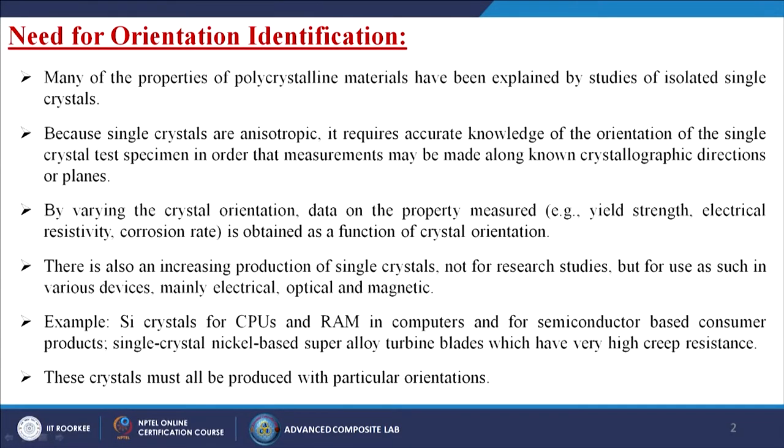As we know, many of the properties of polycrystalline materials have been explained by studies of isolated single crystals, because single crystals are anisotropic in nature, which requires accurate knowledge of the orientations of the single crystal test specimen so that measurements may be made along known crystallographic directions or planes. By varying the crystal orientations, data on the property measured, like yield strength, electrical resistivity, corrosion, etc., is obtained as a function of crystal orientation.